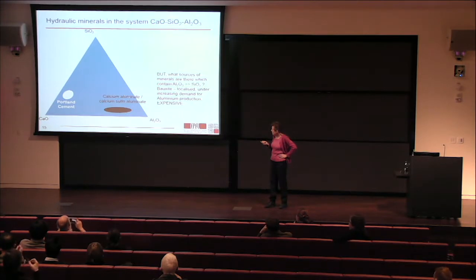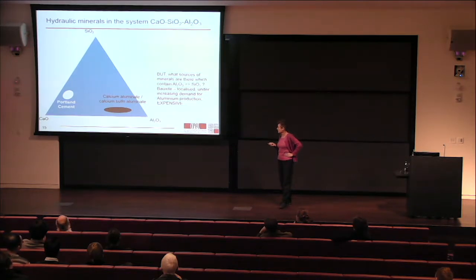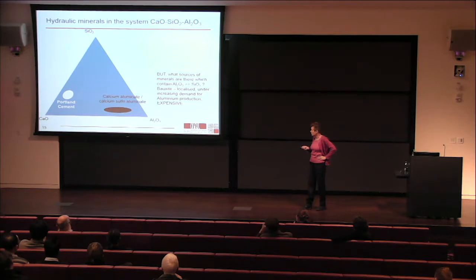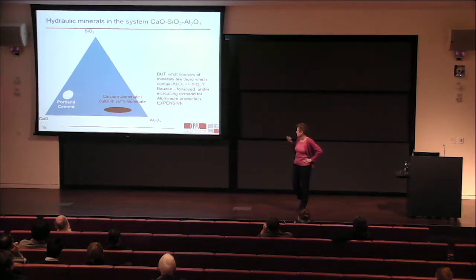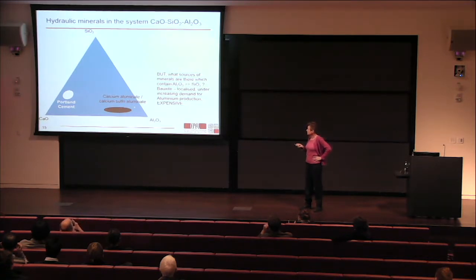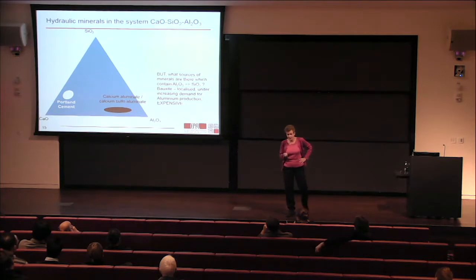So the problem here is that to produce these calcium aluminates and calcium sulfoaluminates, you see now we've got considerably more alumina compared to silicon. And geologically, this is rather more rare. Generally, alumina and silica occur together in nature in roughly the same proportions. If you're going to get sources which contain much more alumina, you've already got to go to materials like bauxite. Bauxites are much more localized. They are under increasing demand for aluminium production, therefore they're more expensive. So if you make cements here, they're going to be a lot more expensive. Calcium aluminate cements, for example, cost today about 5 to 6 times the price of Portland cement.